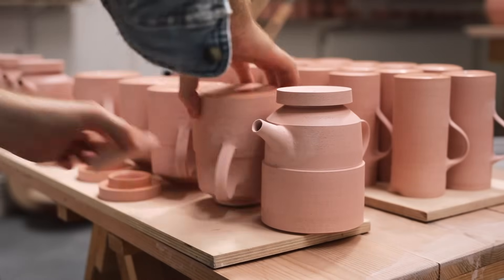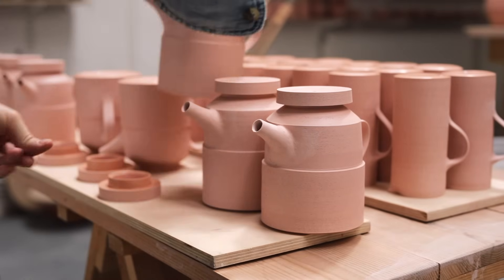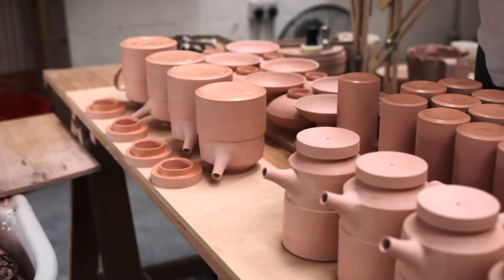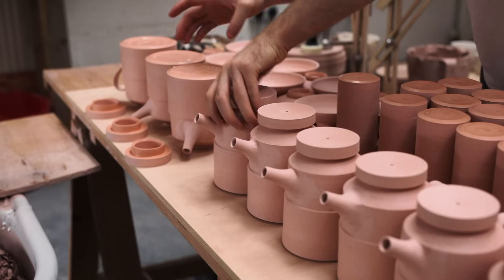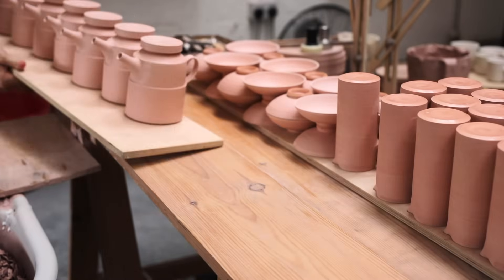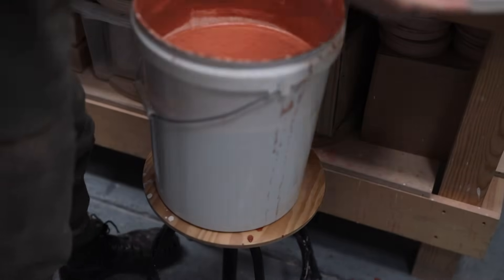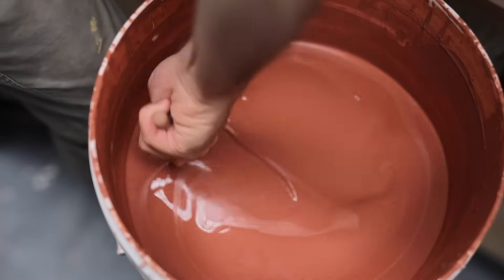After all of the pots have been waxed — and usually this doesn't just include the teapots, but hundreds of bowls and mugs, jars, ink dip pens, ink wells, all manner of things — but after everything has been waxed, it's time to begin the glazing. I'll be glazing these pieces with a feldspathic crackle glaze, which is coloured by 2% red iron oxide, and once reduction fired, will turn a deep dark green colour. And that's one thing you quickly learn as a potter — glazes at this stage often don't look anything like how they'll appear once fired. But first, as I haven't used this glaze for a while, I need to give it a really thorough mix, as all the raw materials this glaze contains — such as feldspar, nepheline syenite, china clay, and red iron oxide — have settled to the bottom.